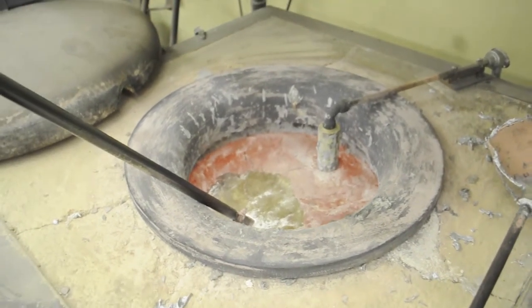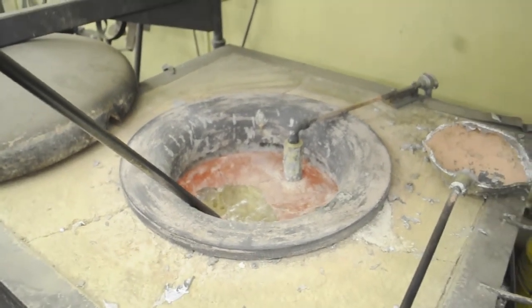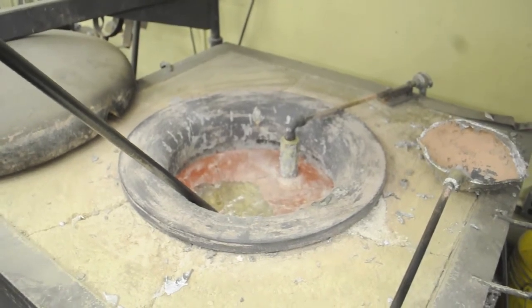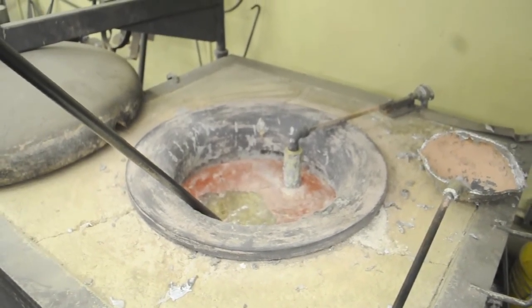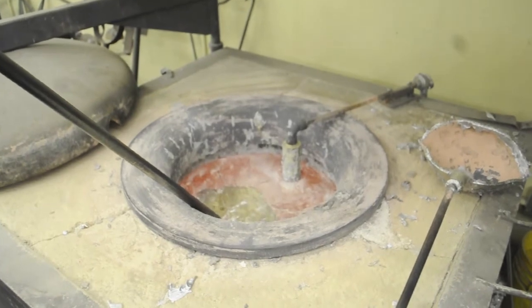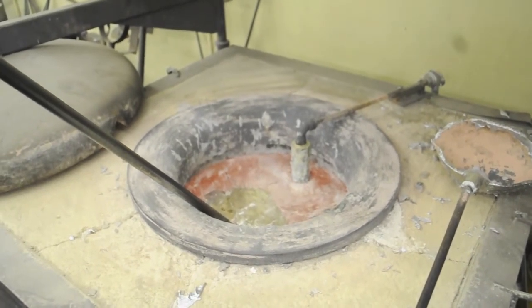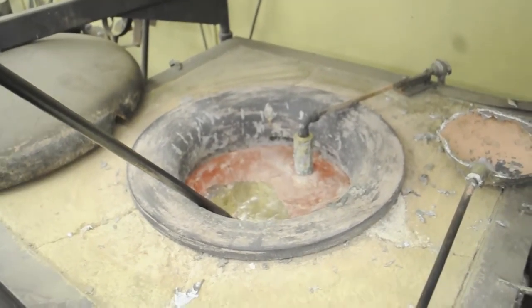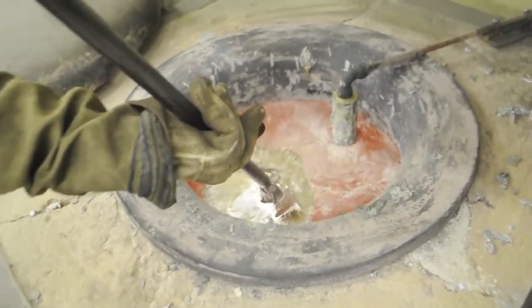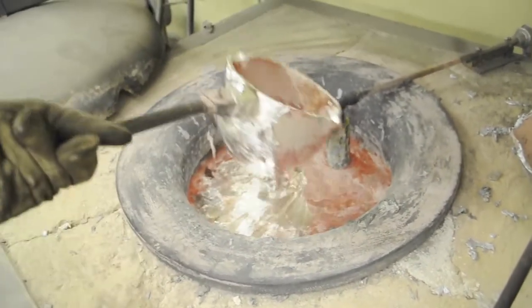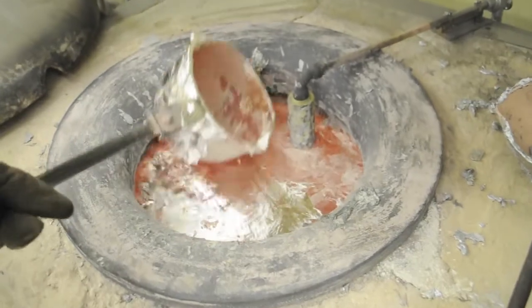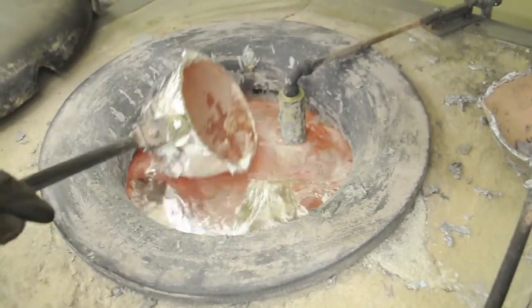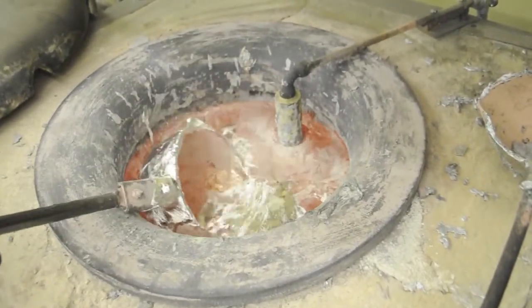So if you put a cold ladle in there and immediately dip out your metal, the cold ladle will absorb a lot of the heat out of the metal and you'll lose a bunch of your superheat and you may not get a complete part because you cooled the metal off. It only takes about 20 seconds or so. Okay, now I'm going to pull the ladle out and I'm going to push the dross out of the way. I don't want to dip out the dross. I would just like to leave the dross in there.